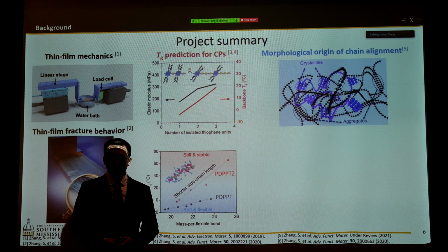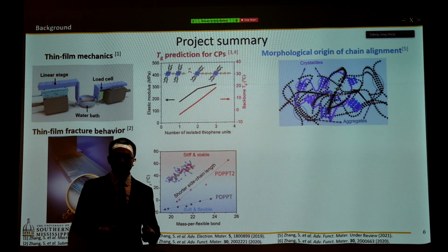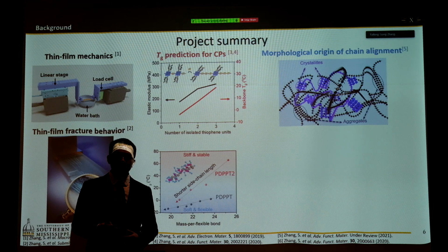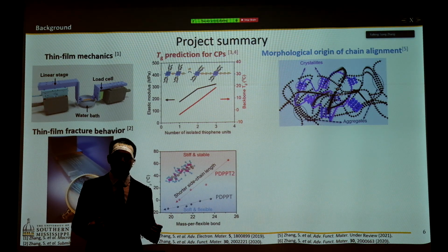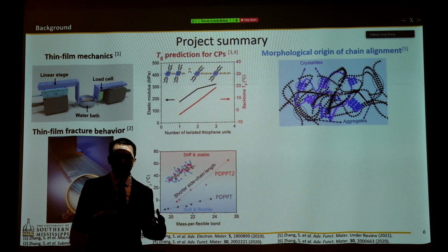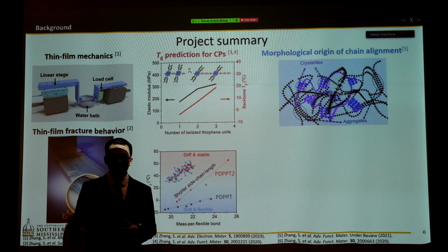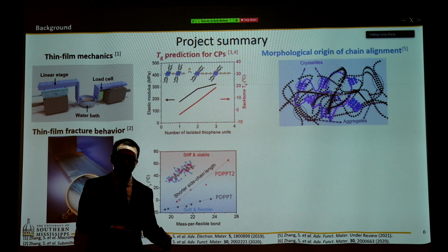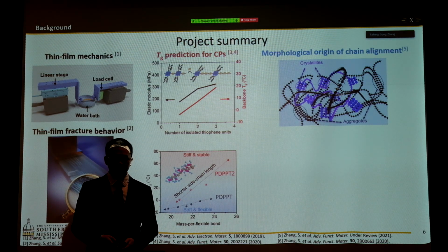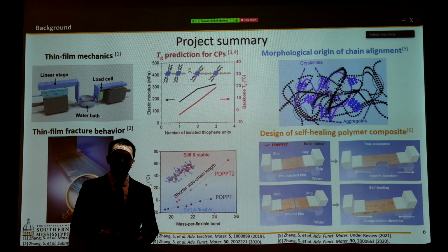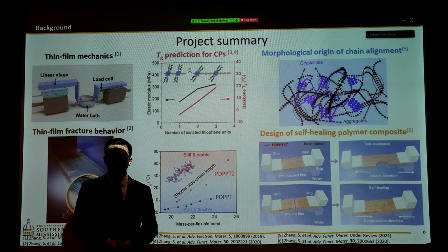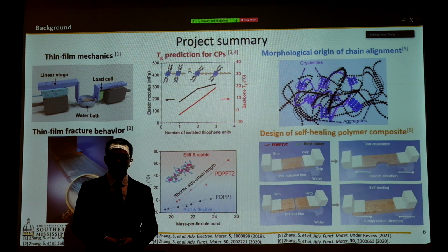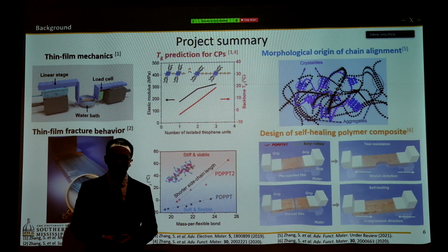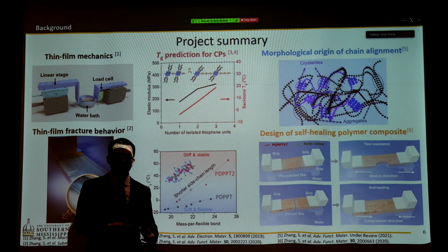I also try to understand the alignment mechanism for the donor-acceptor polymer under alignment. And since we have to make these polymers into flexible electronics, and morphology will influence the electrical property, we need to build this morphology and electrical performance relationship. We also have a paper published together with Dr. Story and Dr. Nazarenko's group, where we built this polymer composite, and it not only has mechanical tear resistance and self-healing property, it also has self-healable electrical performance.